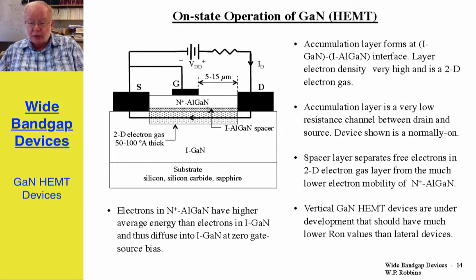The spacer layer is essential because it separates the free electrons in the accumulation layer from the aluminum gallium nitride, which is heavily doped. This is essential because without the spacer layer, the ionized donors right at the interface would influence the mobility of the electrons in the two-dimensional electron gas and greatly lower their effective mobility. But by having the spacer layer here, we greatly diminish the influence of those ionized donors, and so the electrons in the accumulation layer or two-dimensional electron gas take on essentially the same mobility as electrons in the intrinsic gallium nitride bulk, and that is significantly higher than the mobility in the N+ aluminum gallium nitride by a factor of 4 or 5 or more.